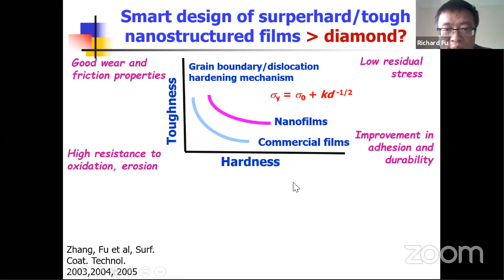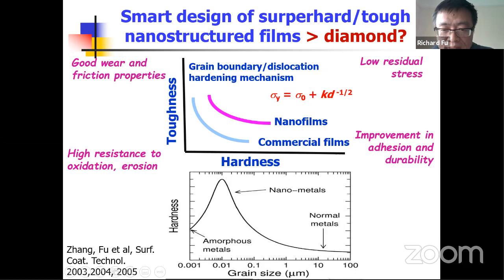And along with reducing the grain size, we can achieve a lot of different properties of the film. Well, there is also always the question that if we continue to decrease the grain size, will the Hall-Petch effect continue to hold? Will the hardness or strength continue to increase? Well, there is a critical point, which is about 10 nanometer or 20 nanometer, depending on materials. Below this critical size, the material becomes much softer. We normally call it the anti-Hall-Petch effect because the grain boundary or amorphous phases become much more dominant. Then the material becomes much softer through the grain boundary sliding mechanism. So that means if we can prepare the film with a grain size of tens of nanometers, then we can achieve very good hardness.